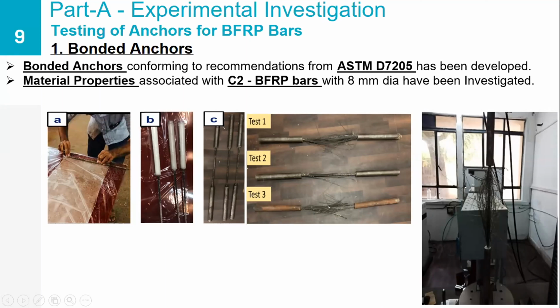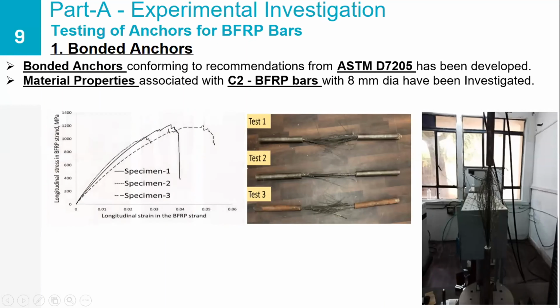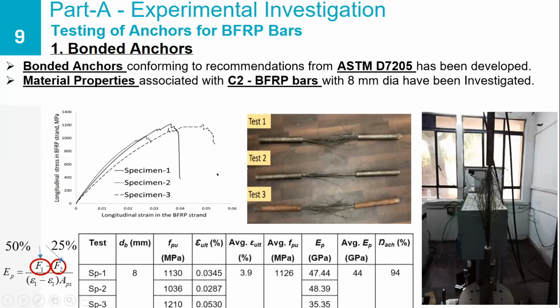And these are the specimens that have been tested using those FRP bars with the bonded anchors. So you can see the rupture of the fiber over the gauge length of the specimens. And so basically the fibers separate from the polymer resins and they rupture, causing the failure of the bar. So that is the desired failure.